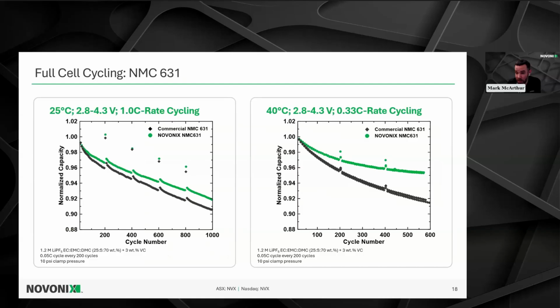I'm showing here normalized capacity for each cell type. And what you start to see is that the material that we made at NOVONIX via all dry zero waste processing actually outperforms this commercial high quality NMC 631, both at 25 degrees Celsius as well as 40 degrees Celsius at the lower rate. So what you can really start seeing is all dry zero waste processing can give you a platform from which you could build upon to make a material that would meet your specific requirements, which is great. And you can do that at a lower cost without generating any waste streams.